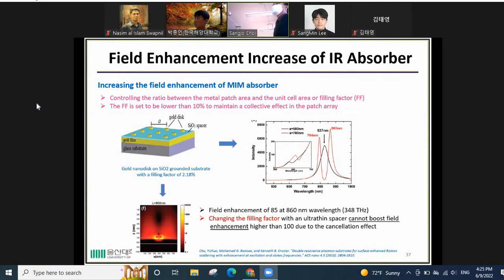So for increasing the field enhancement from the MIM absorber, normally people control the ratio between the metal pads area and the unit cell area, or we call it the filling factor. This structure is using gold nanodisk on a silicon dioxide grounded substrate with a filling factor of 2.18%. And also this is the electric field enhancement. It is showing 85 at 860 nanometer wavelength or 348 terahertz. So from this we can see that changing the filling factor with an ultra thin spacer cannot boost field enhancement higher than 100 because of the cancellation effect from the structure and its image in the reflector.